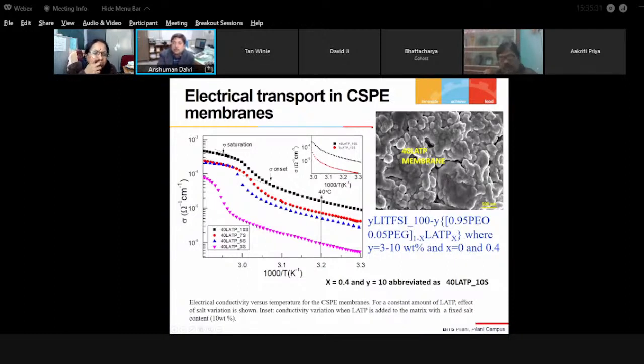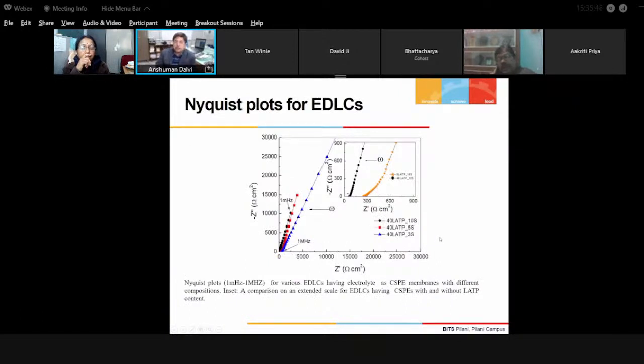And this kind of slurry, which is finally appearing, was finally given a shape by a hot polymer press machine, and with 200 micron film the supercapacitors were developed.